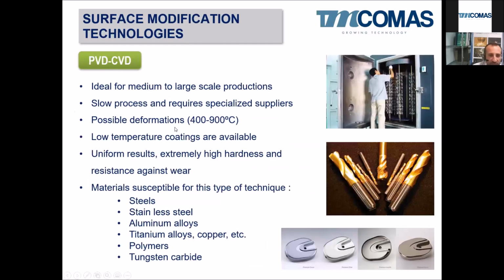Okay. PVD and CVD. PVD stands for physical vapor deposition and CVD for chemical vapor deposition. These two technologies are quite advanced. They take place in a reactor or in a chamber, which is under vacuum. That means that we have to work in batch productions. It's ideal for medium to large scales, since here, as you can see, we can place hundreds of small parts into that reactor, and we can perform that coating to all of them at the same time.